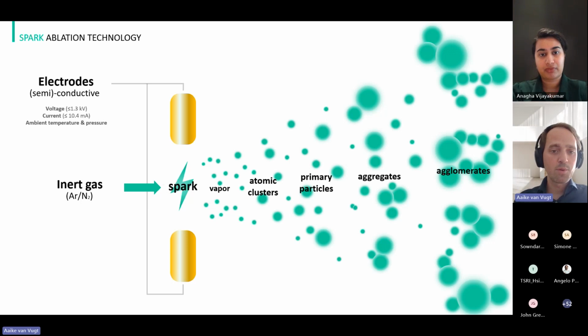This is a continuous process. Basically, every spark is a batch process. But if you do 300 or maybe a few thousand sparks per second, it feels like a continuous process of production of nanoparticles. The evaporated material is carried away with an inert gas. We use mostly argon or nitrogen, but you can play around with different gas compositions. Adding oxygen to the gas will help you oxidize the nanoparticles very rapidly. So there are all kinds of things you can play with.